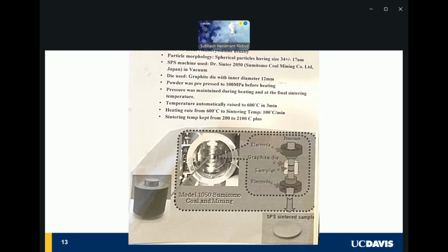The other technique, which we have been very happy with for a lot of reasons, and this is equipment from Sumitomo Coal and Mining, the Dr. Sinter model, is basically a machine which utilizes a graphite die or any other die you may have, and you put powder inside it in this area that I have shown here. And then in the area that you squeeze the sample, you essentially get a dense disk from powder to disk. And the sintering temperature can vary. I mean, you could be as low as 200-300.